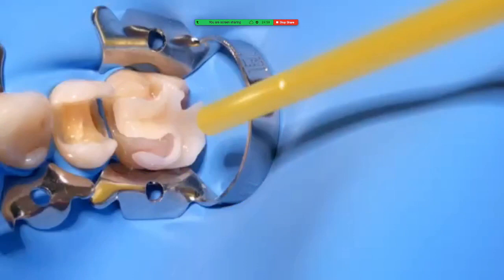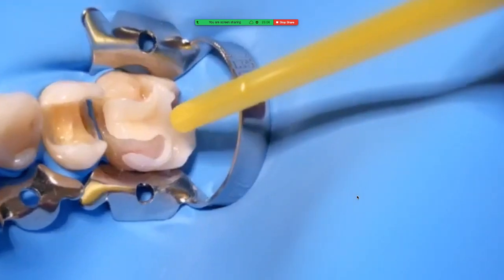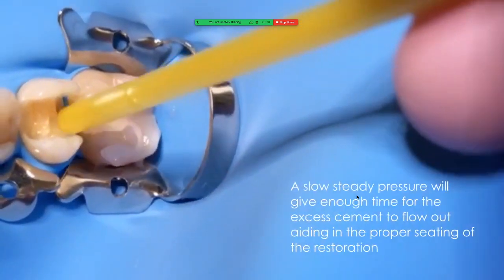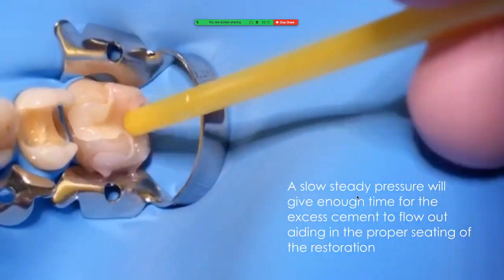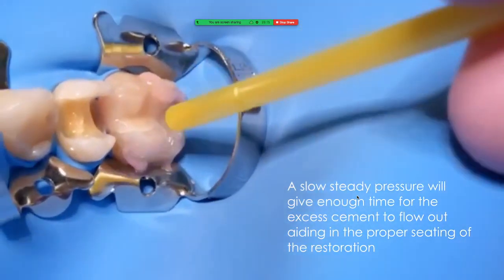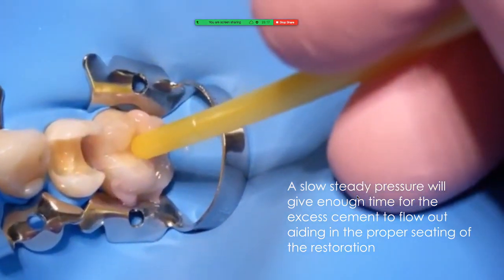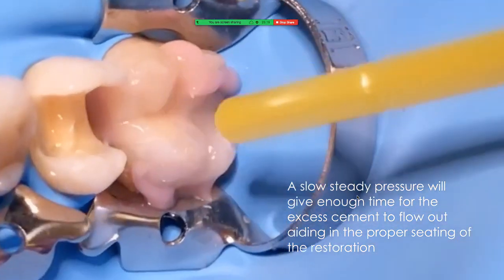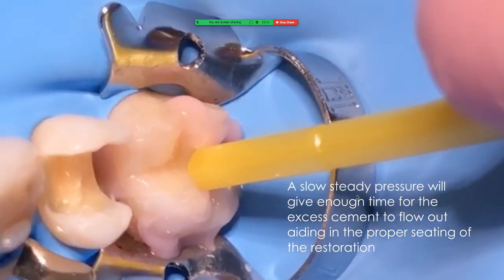Self-etch adhesive is used for immediate dentin sealing. Self-primer applied using light rubbing for 20 seconds. And slow, steady pressure will give enough time for excess cement to flow out, aiding in the proper seating of the restoration. A glossy surface after self-etching priming means that the primer has sealed the dentinal tubules.